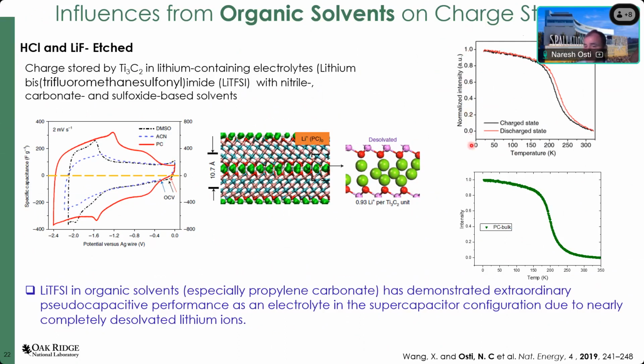elastic intensity as a function of the temperature using the quasi-elastic scattering technique from the charged and the discharged system, which I have shown here. The scattering pattern exactly looks like the scattering pattern that you would get from pure bulk propylene carbonate. That means that yes, it's true that lithium ions shed their solvent shell once they get in between the MXene layers.